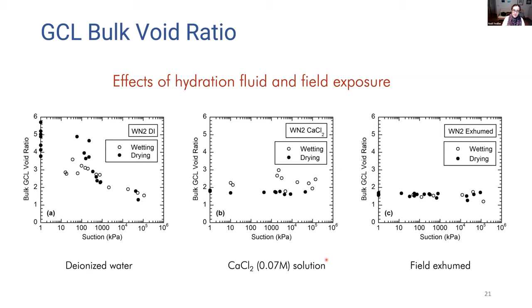We also looked at the bulk void ratio, which is a parameter that's similar to the regular void ratio for soils, and looked at effects of hydration fluid and field exposure. This is again for this WN2 material, the needle punched woven, non-woven geotextile reinforced material. In this case, these are plots of bulk GCL void ratio versus suction. And we have data shown here for deionized water, the calcium chloride solution, as well as the field exhumed material.